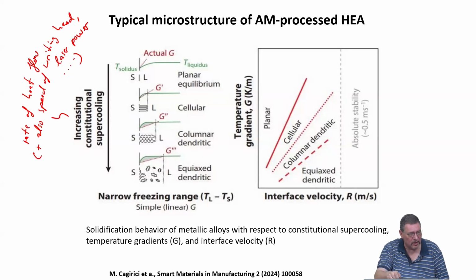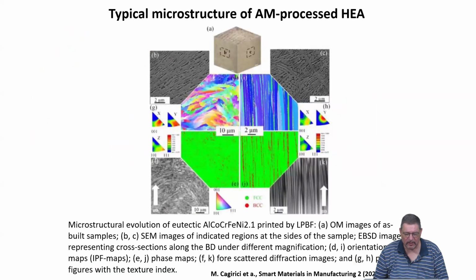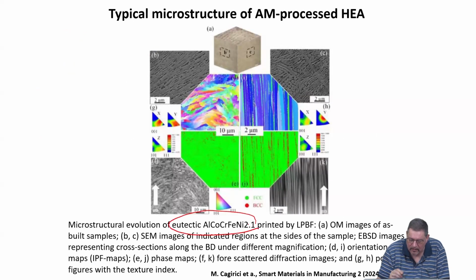is more related to Bridgman solidification, to something which might be very dendritic, which is similar to what you get in arc melting or laser cladding. And obviously one does not like to have very dendritic microstructures. But yeah, this is what you typically get in the microstructure evolution of an AM, additive manufactured, processed high entropy system, and that's actually now a two-phase high entropy system. It's a eutectic high entropy system.